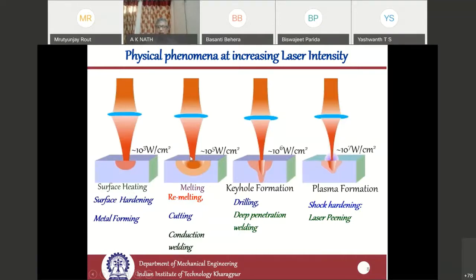If you go for higher laser power in the range of 10 to the power 5 watt per centimeter square, you can do melting. This can be used for laser surface remelting, cutting, conduction welding, as well as surface alloying. When you go for slightly higher power density, the melted material starts evaporating, and the vapor pressure generated can create a keyhole. Through this keyhole, you can realize deep penetration welding as well as drilling.